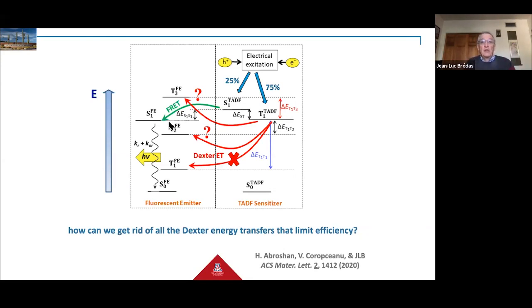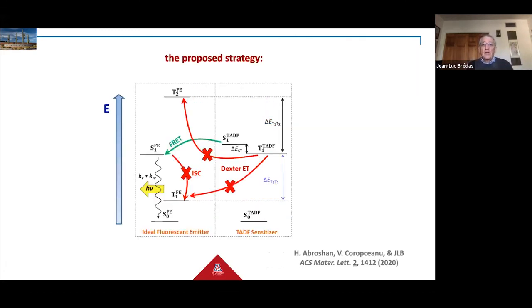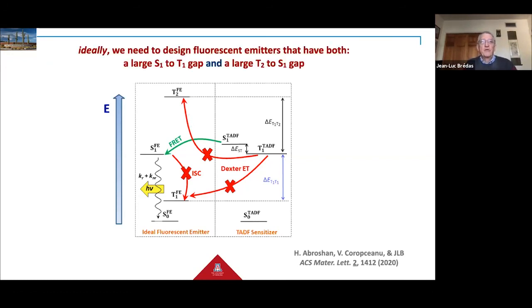And so how can we get rid also of those other energy transfers? And that's the proposed strategy that comes out of Hadi's paper, which is the fact that what would be really interesting would be to design fluorescent emitters in which the second triplet excited state is very much higher in energy with respect to the lowest singlet excited state, which means that then the Dexter energy transfer would be too much uphill and would be negligible as well.